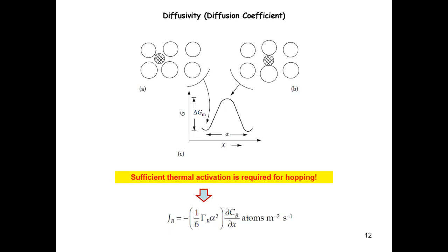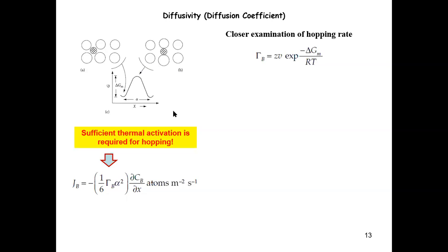So we see that the hopping rate is basically proportional to the probability that you are initially in this particular valley and get sufficient energy to hop over this barrier into another valley. And this is what determines the hopping rate. Now, whenever we see some activation energy or energy barrier, we know this is the right equation to use. So we use the Boltzmann type of equation, because this equation typically gives you the probability if you have two competing effects.